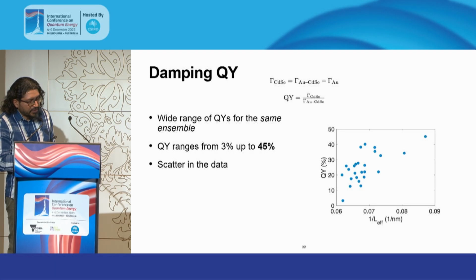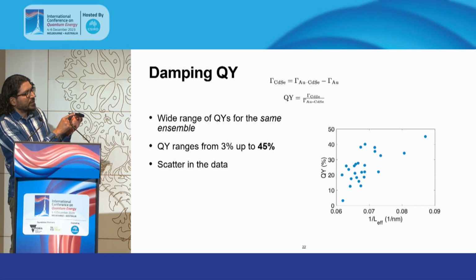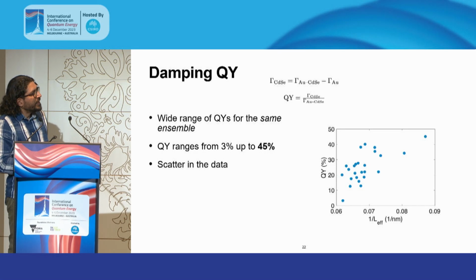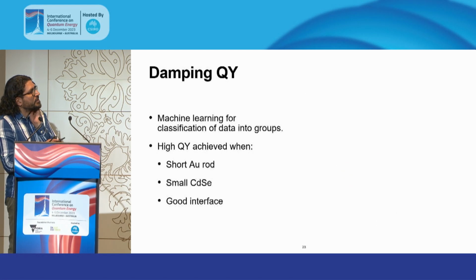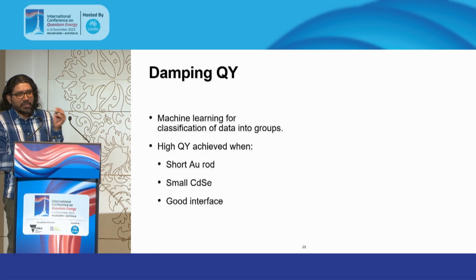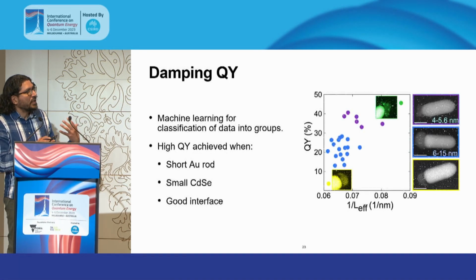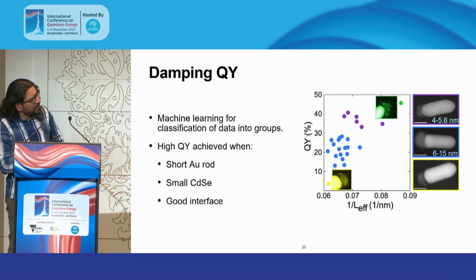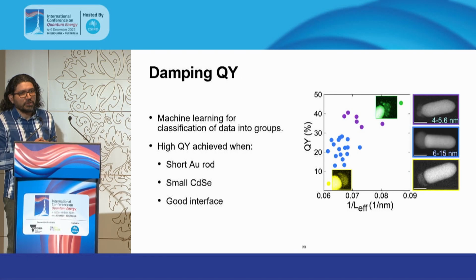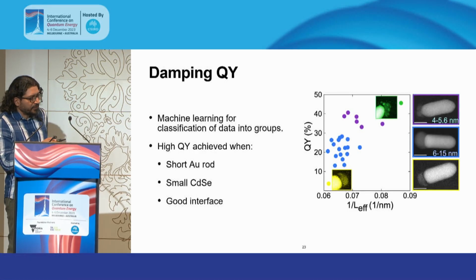The data here, as you can see, collected over many particles, is scattered when we plot the quantum yield versus the average distance of the electrons to the surface. So we fed this data into a machine learning classification algorithm that sorted the data into at least 5 clusters. The advantage of doing these experiments in the electron microscope is that for every data point, we can go back and get information, as I said before, on composition, geometry, and quality of the interface.